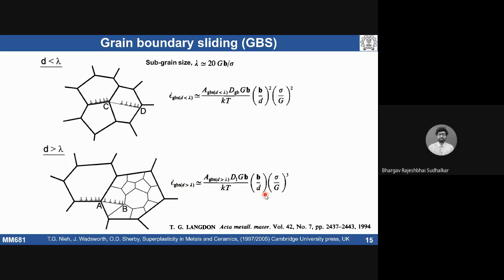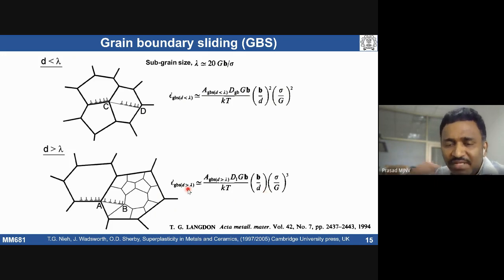So, sir, this constitutive equation tells us which kind of creep mechanism will be used to accommodate in different grain sizes, right? It's not necessary. Most of the times in coarse grain materials, diffusion creep is going to accommodate the grain boundary sliding. Depending on grain size and temperature, the mechanism is going to change. Within grain boundary sliding there are two mechanisms, Lifshitz sliding and Rachinger sliding. Most of the times fine grain size materials will experience this kind of grain boundary sliding, so people call it close to Rachinger sliding. This equation is close to Rachinger sliding, and that one is close to Lifshitz sliding. So these are generic constitutive equations given based on grain size.